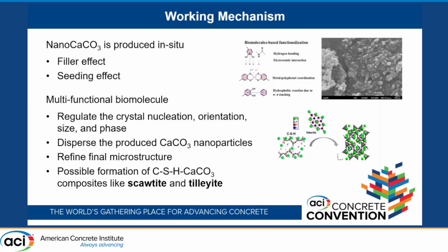The biomolecule that we use also has several different functions during the process. It regulates crystal nucleation, orientation, size, and phase. It disperses these nanoparticles throughout the mix, which allows us to keep more CaCO3 particles in the mix. It refines our final microstructures of these particles, and it could possibly form other composites.